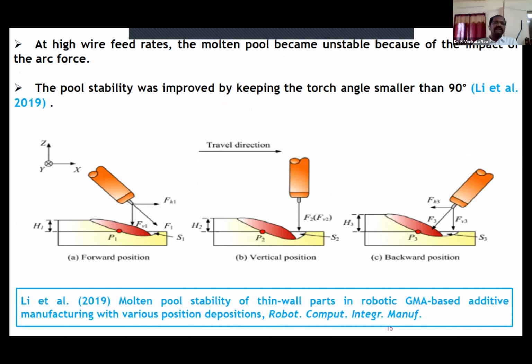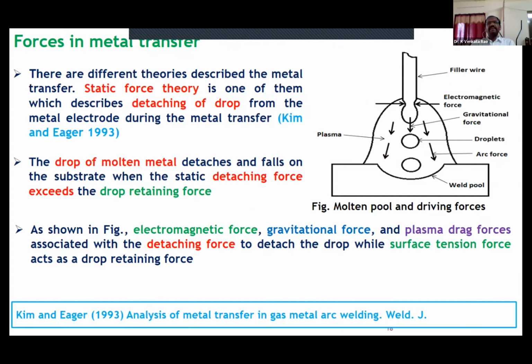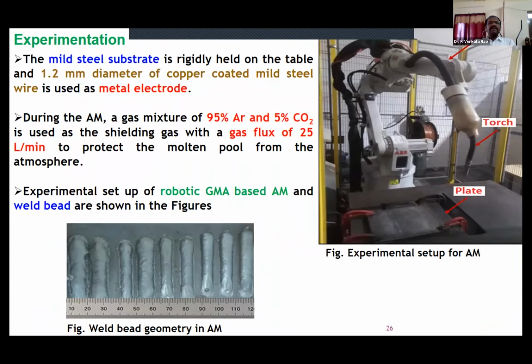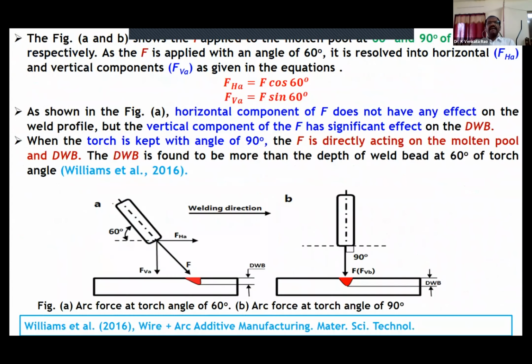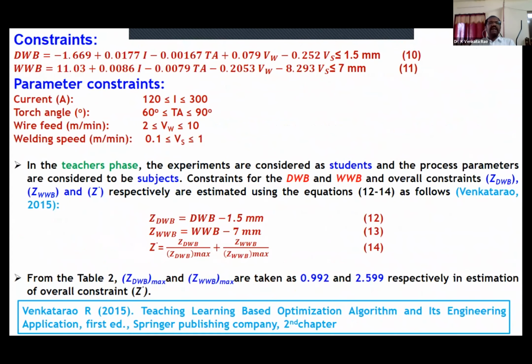In the previous work, this person found that pool stability was improved by keeping the torch angle smaller than 90 degrees. So like that, we conducted the experiment between 60 and 90 only. And also here is the constraint of that input, the torch angle.